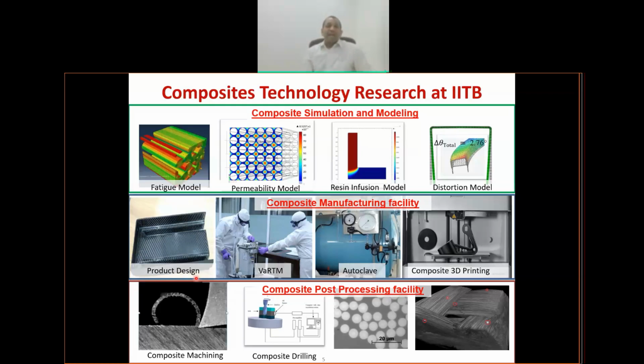And again, composites are used in aerospace. As you may know, the Boeing Dreamliner has the majority of its structure made up of composites, carbon fiber composites. And the carbon fiber composites have the special weight to strength and weight to stiffness advantage. So they weigh very little and they are extremely stiff and extremely strong. And that makes it possible for you to have very light structures which will be able to withstand a lot of stresses without deforming. And that's why aerospace is going to embrace composites moving forward in a much, much bigger manner. This also is a huge challenge because once you are having composites made up of polymers and fibers, there's a huge difference in their stiffness, strength, and other things. And thus you have a material which is varying in stiffness, especially very drastically.